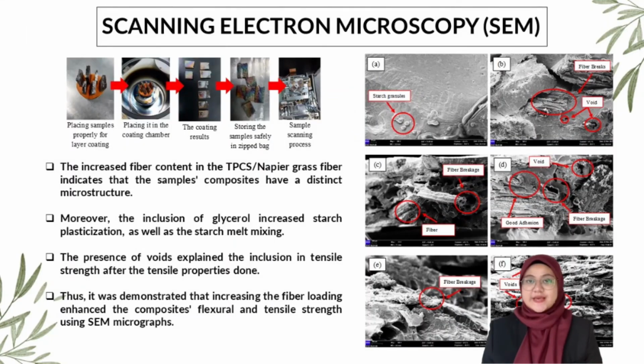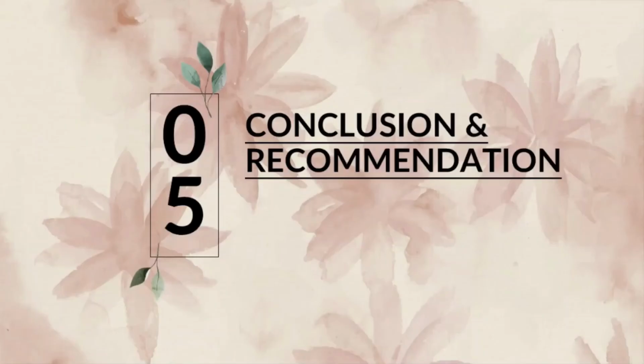In terms of SEM analysis, it shows that the increasing fiber content in the TPCS and Napier grass fiber composites indicates a distinct microstructure. Moreover, the inclusion of glycerol increased starch plasticization as well as starch melt mixing. The presence of voids explains the reduction in tensile strength after the tensile test is done. Thus, it was demonstrated using SEM micrographs that increasing the fiber loading enhanced the composite's flexural and tensile strength.